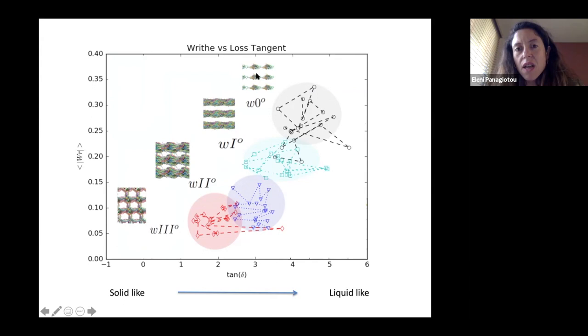Right. So if you had such big writhe in a melt, the diffusion would be more difficult, I suspect, because you have a self-entangled chain in the presence of other chains. So it is difficult for it to move in general. But if it doesn't have anything surrounding it, then it will attain a random conformation, and we know that as the length increases, the entanglement complexity of the random conformation will also increase. But it is more a matter of how big the chain is. So maybe that's what you asked from the beginning.